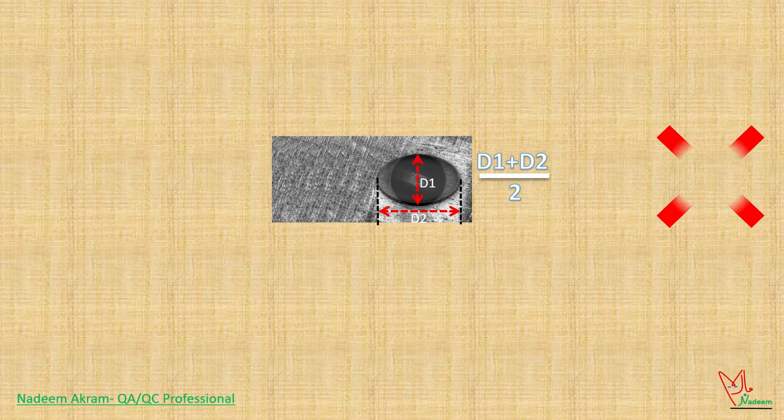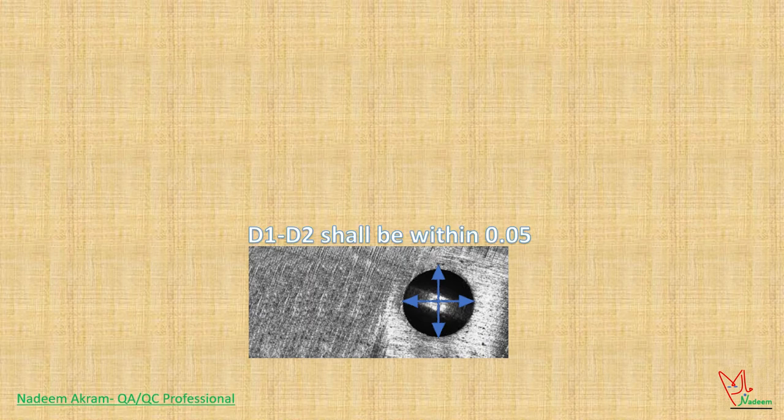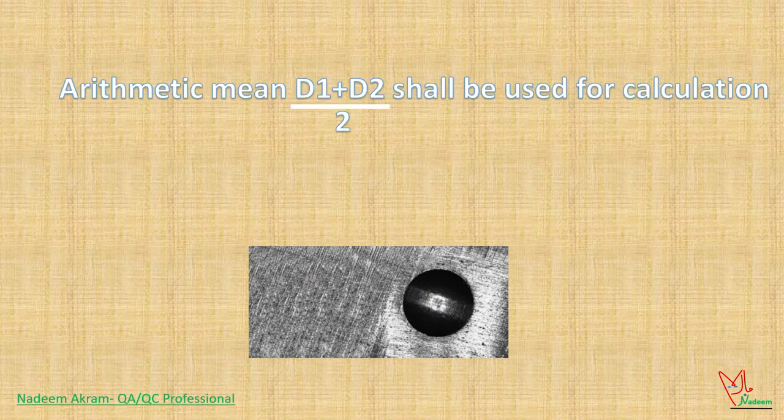Perpendicular, 90 degrees, to each other shall be measured to within 0.05 millimeters. The arithmetic mean of the measurement shall be used for the calculation.